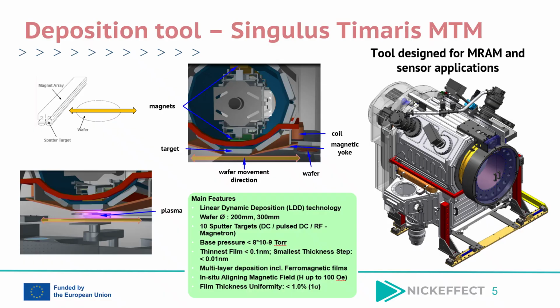The rotating drum contains 10 sputtering targets, enabling sequential deposition of complex multi-layer stacks without breaking vacuum. In the center part of the drum, two dedicated magnet configurations are used for ferromagnetic and non-ferromagnetic material deposition. The deposition system supports both DC and RF sputtering processes and enables deposition of ultra-thin films with excellent thickness and interface control. Such a machine design enables highly reproducible growth of complex multi-layer thin films and provides industrially compatible processing for advanced MRAM and sensor technologies.